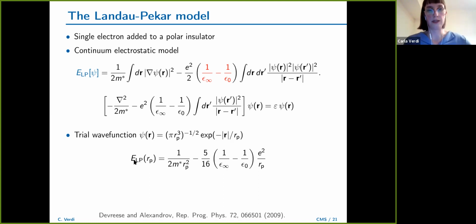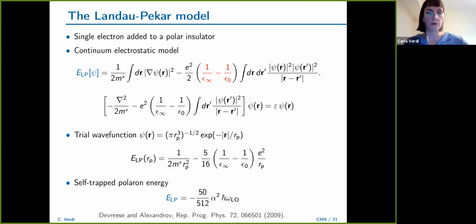This is the energy of the Landau-Pekar polaron as a function of the polaron radius. So you have the kinetic term and the electrostatic term, and the sum of these two terms is negative. There will be a radius that minimizes the energy, and that will be our actual self-trapped polaron energy. So from this minimization, we can get the polaron radius and we can get the polaron energy.